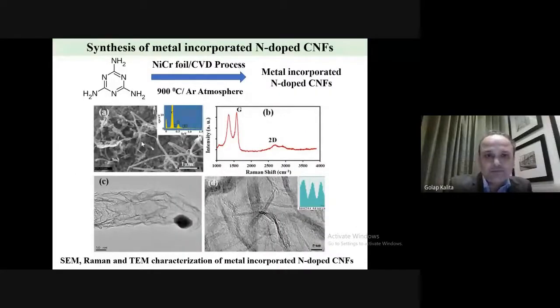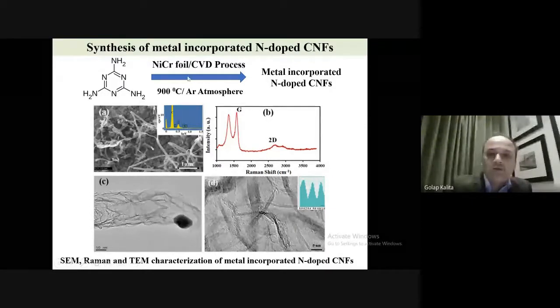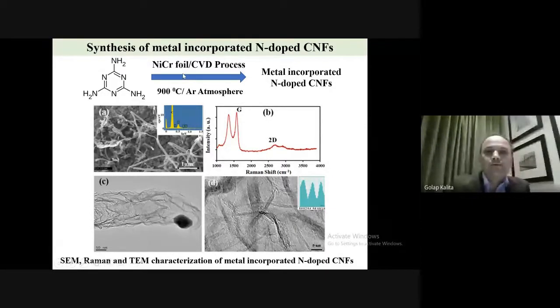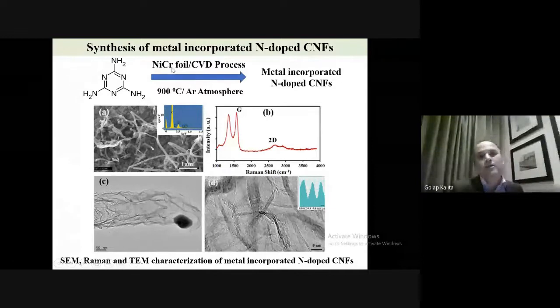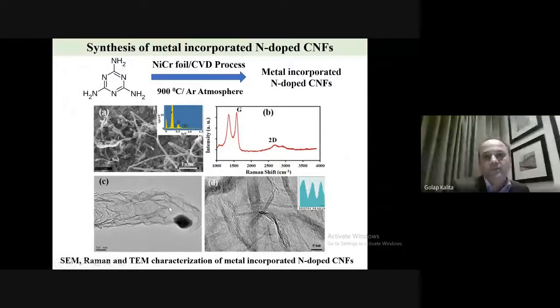Then I come in. We synthesize metal-incorporated nitrogen-doped CNF. In this case, we use melamine, and we grow some interesting structures. These are very highly dense and randomly oriented graphene-like structures. Then you have metal incorporation in this, and we synthesize this on bimetallic nickel chromium foil, so it's two different metals. It helps to grow this type of structure.